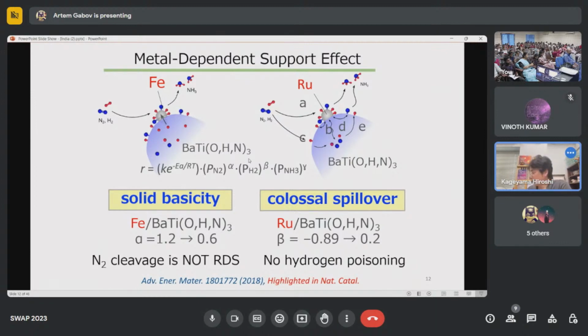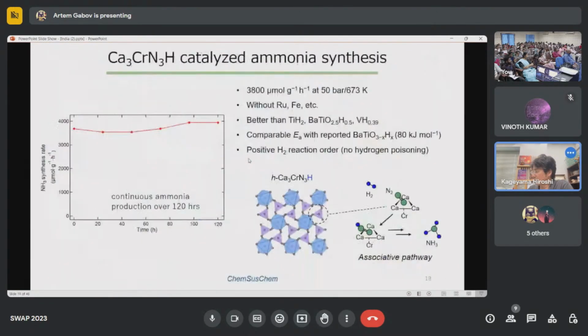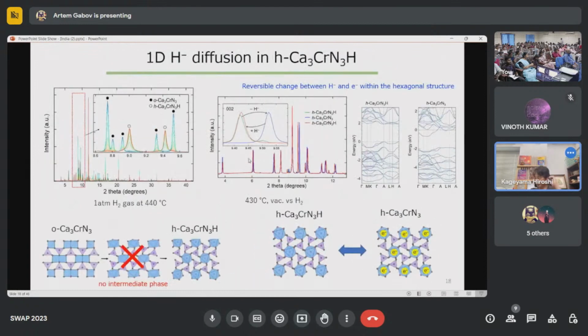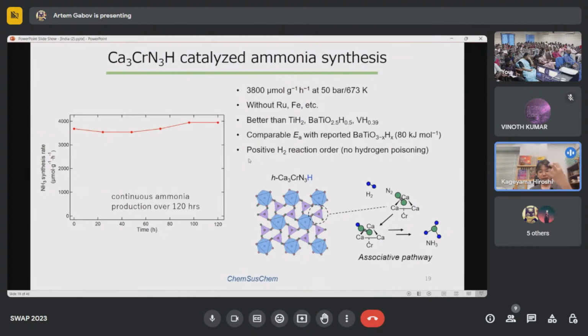So maybe we may think that this hydride nitride compound shows similar advantages. Namely, hydride can migrate, and this can avoid the problem of hydrogen poisoning. Then we expected that maybe nitrogen directly comes into this hydride and reacts to form ammonia gas. But unexpectedly, our DFT calculation and so on revealed that the reaction pathway is different. To make the story short, we found that the triangle unit, I mean the chromium N3 unit, is the most important part of the structure.